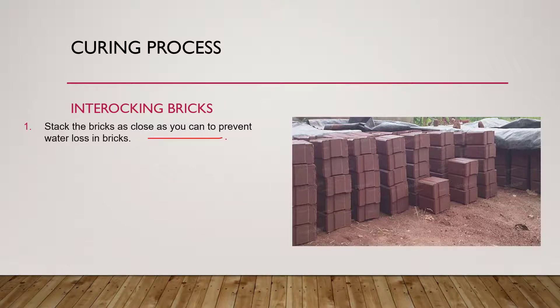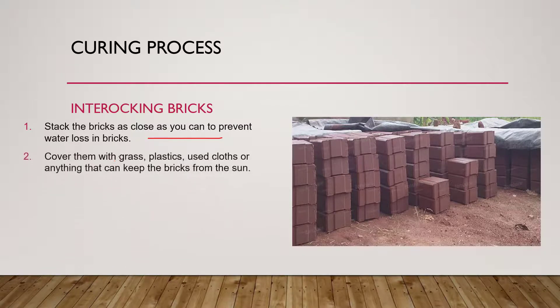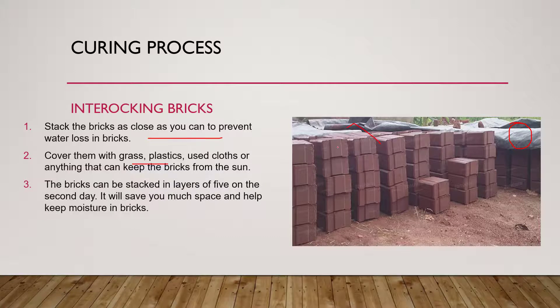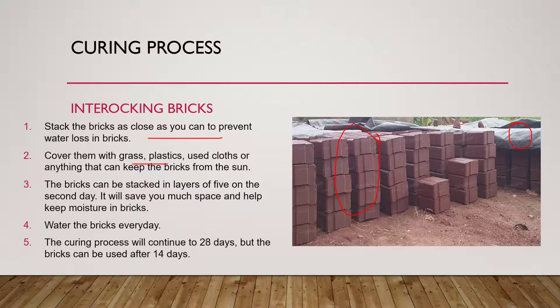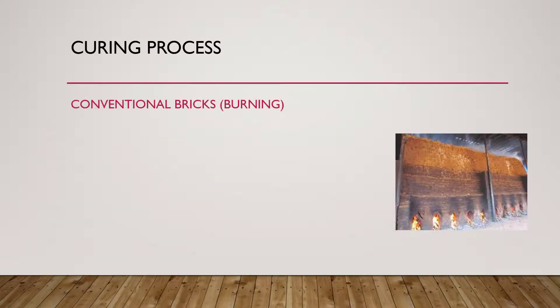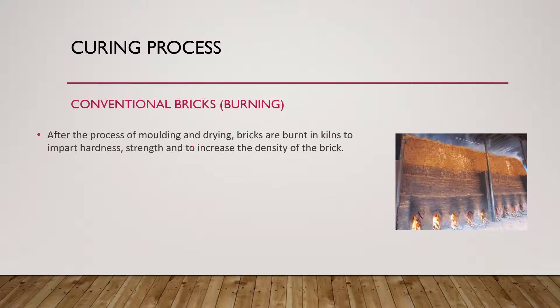For curing interlocking bricks, stack the bricks close together to prevent water loss and cover them with grass, plastic sheets, or used cloth to protect from sun. They can be stacked in layers of five from the second day. Water the bricks every day — the curing process continues for 28 days, but bricks can be used after 14 days.